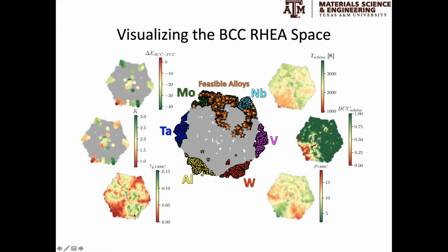Alloys that are low density, on the other hand, tend to be weaker. It turns out that alloys that are strong also tend to be BCC, so these are strong refractory alloys. You can tell that by looking at all these constraints, and if we put them together at the end, we get a very small region of the feasible space.